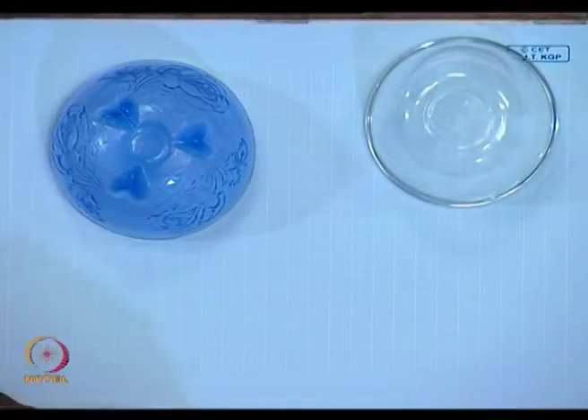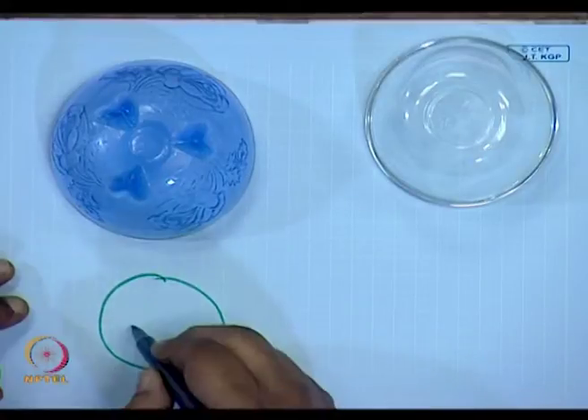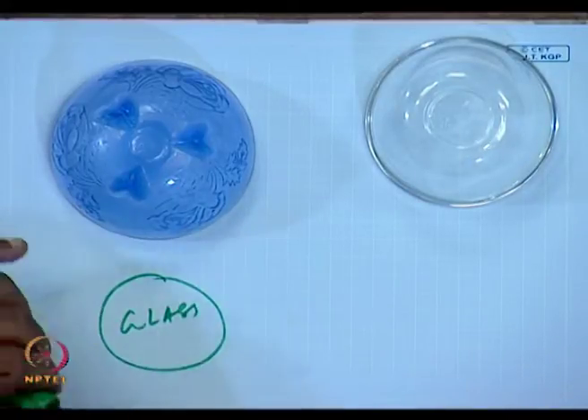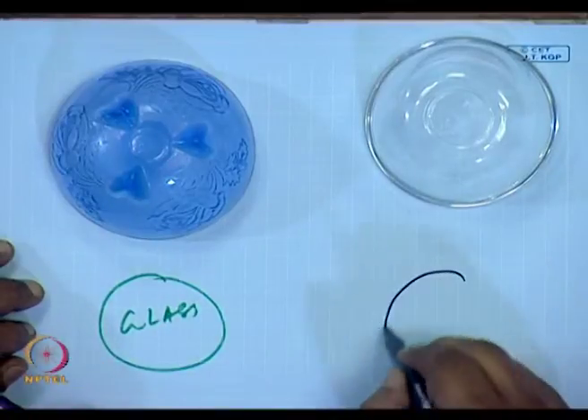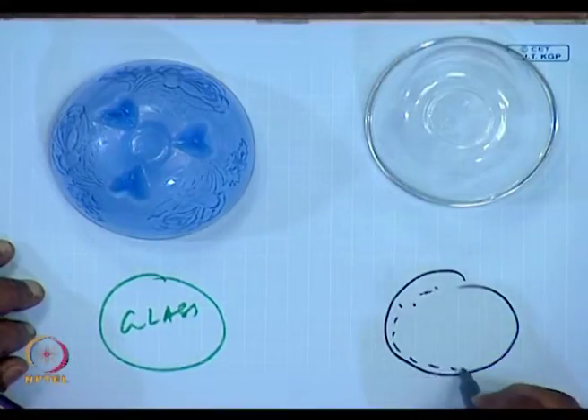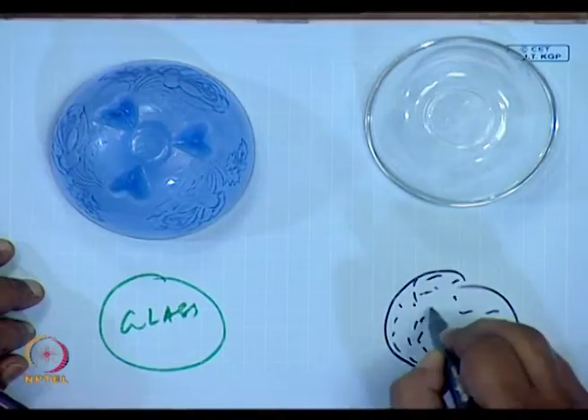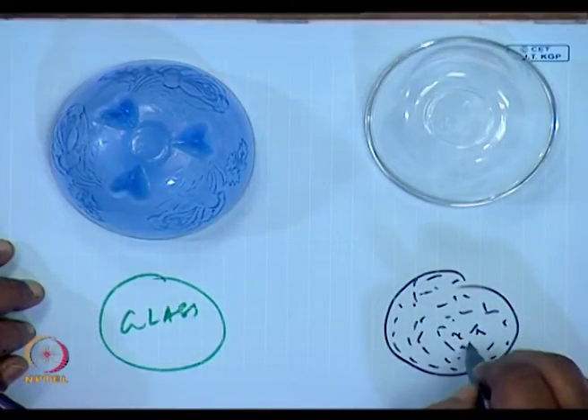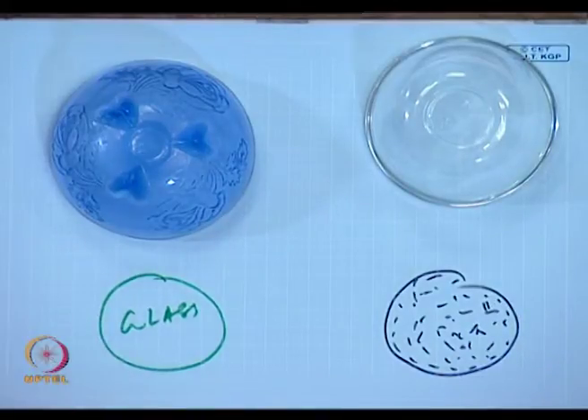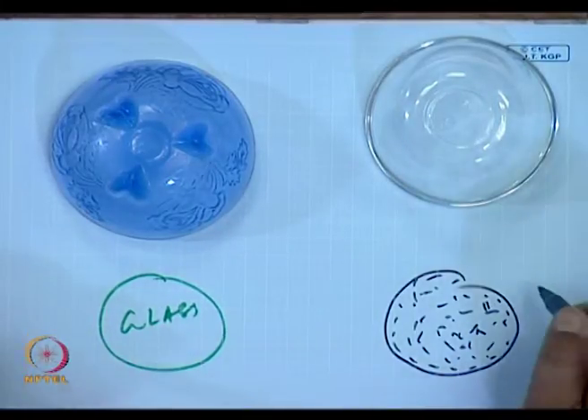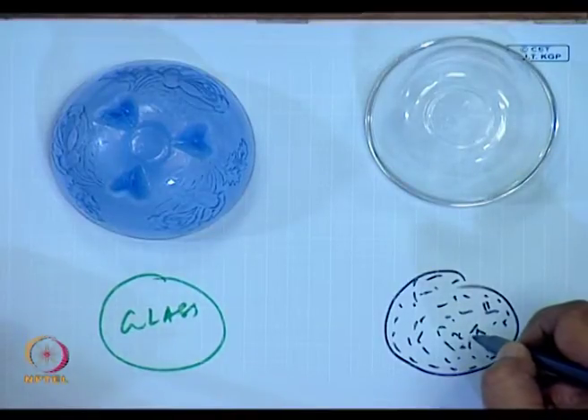If I look at the microstructure of these two, and if I take a small broken piece and look at these two under a microscope, to repeat it, I will see only a glass over here. But over here, what I will see is a glassy matrix with very ultrafine particles distributed right through, of sizes less than lambda by 4, which gives it exceptional strength, exceptional thermal cycling property, and they don't break.